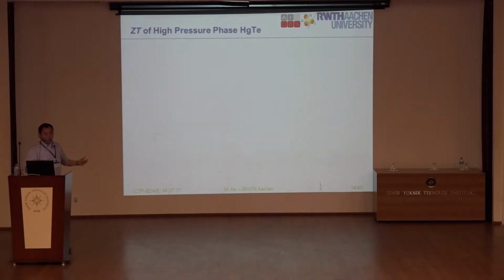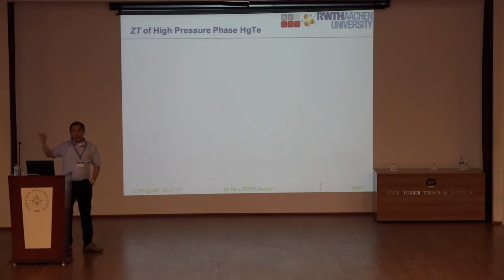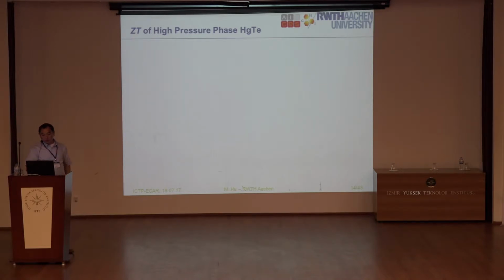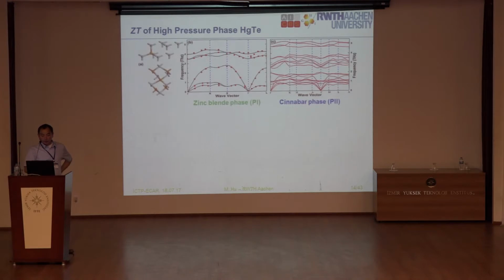So then, since mercury telluride has a different pressure phase, if you continue to increase the pressure, the intuitive idea is to study the thermal transport at a high pressure phase, right? What we talked about in the past is just the zinc blende phase, which is at normal pressure, and then another phase is called the cinnabar phase at high pressure. Of course, the structure becomes more complicated, and then the phonon dispersion becomes more complicated.